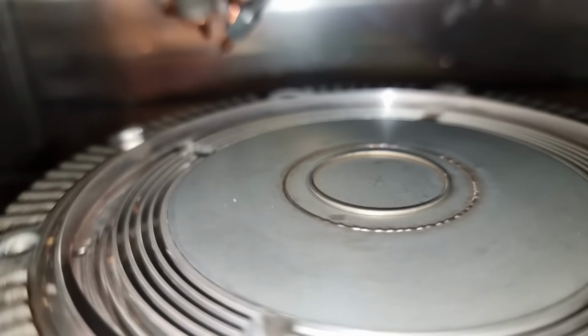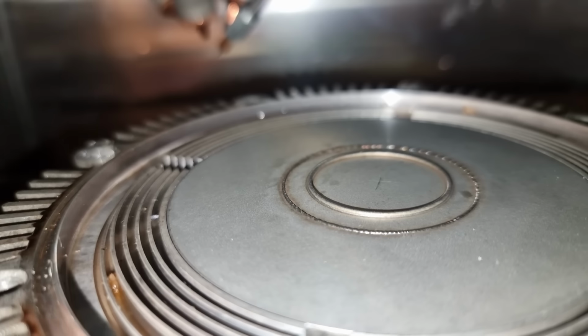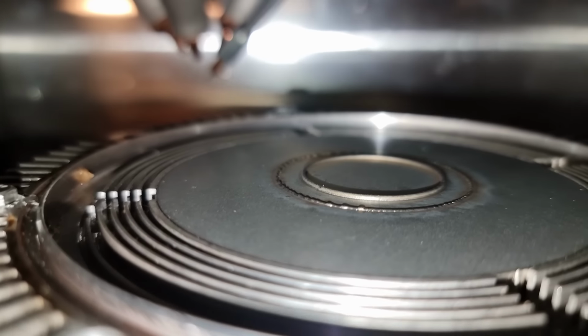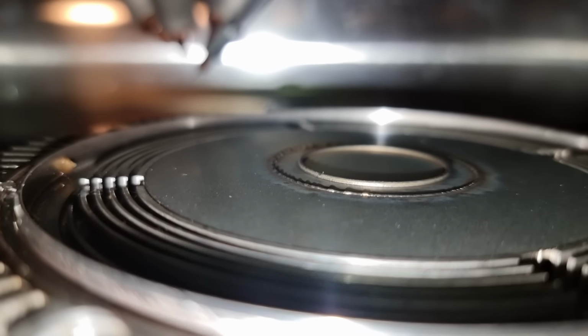Naturally, what would follow would be several tests to see how the layers stacked up, and what you're looking at here is the result of 7 layers which should have amounted to nearly 1mm. Instead, the height was only 0.85mm and the source of it I wasn't too sure of.